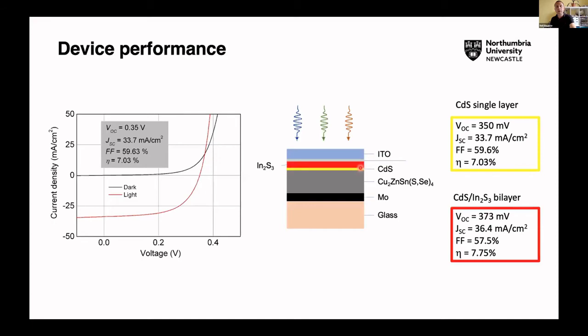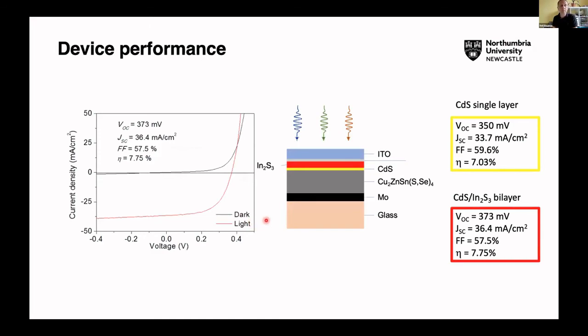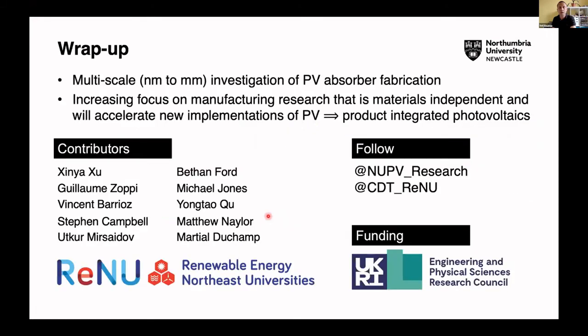And then when you replace that with, first of all, a dual buffer layer, so you have a very thin layer of cadmium sulfide and a much thicker layer of indium sulfide, we get to 7.8%. And in fact, if you take the size of the contacts into effect, that goes over 8%. So that's quite good. When we replace with just indium sulfide alone, we're only around 5.4%. So there's good progress there too, but work to do at that interface. And of course in CZTS, that interface and the defects, that's what it's all about. So that's encouraging, and we'll be able to incorporate a lot of this into that manufacturing knowledge and insights that I presented in the first part of the talk.